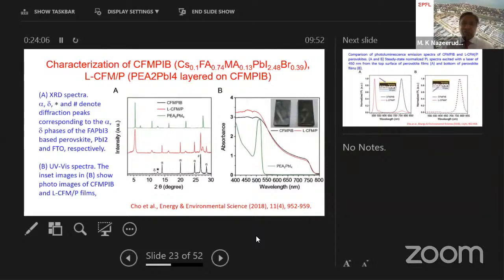As we discussed, the two-dimensional perovskite absorbs only a small portion of the visible light. And the black line is our reference sample, three-dimensional perovskite. And now if we deposit this two-dimensional perovskite on the top of three-dimensional perovskite, the red line is shown here. Now, how do we know that this is happening? If you look at the pure two-dimensional perovskite, which is shown here in green, the top line, this is a characteristic fingerprint line of the two-dimensional perovskite in the XRD data.